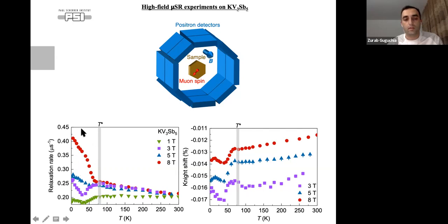So this shows that at low temperatures in high fields, the relaxation rate is dominated by the electronic contribution, because the nuclear contribution does not change with field. So we make the electronic contribution stronger and stronger, the nuclear stays the same. So we dominate here with the electronic response.